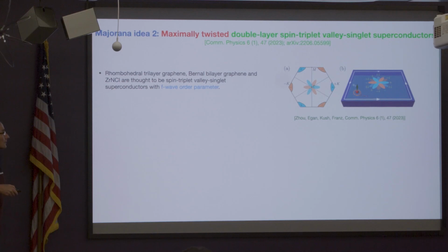The only possibility is to break the spinless time reversal symmetry. And that's exactly what this proposal that's been dreamt up by my postdoc Benjamin is about. So the idea is to follow the construction in twisted cuprates and form a bilayer of this type of material, again, close to the maximal twist angle, which in this case will be 30 degrees, not 45, but 30, because this is hexagonal Brillouin zone.